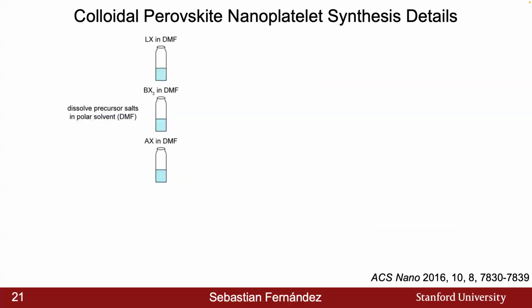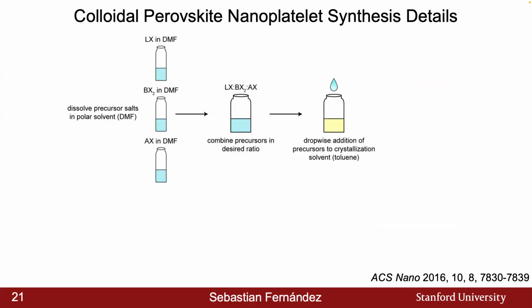Okay, so how do we go about synthesizing these perovskite nanoplatelets? In general, we can dissolve these precursors, so the ligand species, the metal species, and the A-site bulk cation species, in a polar solvent such as DMF. We combine them in a proper ratio to create the particular perovskite nanoplatelet that we want to synthesize. And then by dropwise adding these precursors to a crystallization solvent, in this case the authors use toluene, under vigorous stirring, we can actually see the instantaneous platelet formation.